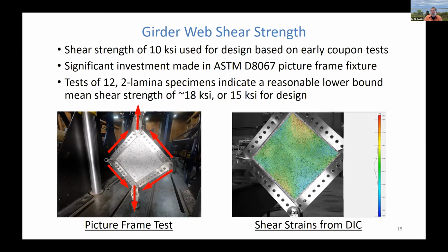I haven't talked about that yet, didn't talk about it in the last presentation, other than to say that these girder webs have ±45 E-glass on them. They're a foam core web, so we can use less FRP and we can still prevent buckling there. And the design, we believed to date, has been pretty conservative. We used a shear strength for those webs of about 10 KSI.